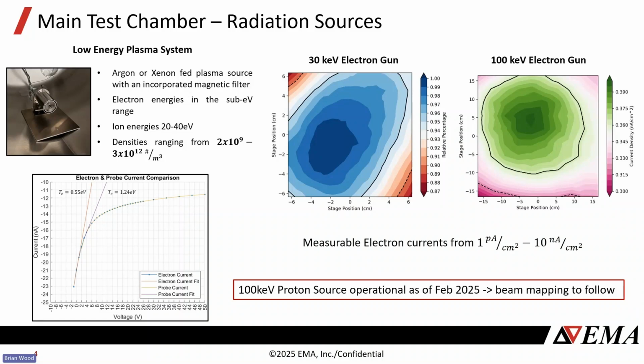Just a little bit more detail on the radiation sources. The low energy plasma system, or LEPS, is basically that LEO simulator. You get ion energies between 20 to 40 eV. It's got a magnetic filter incorporated into it, and what that does is it only allows these sub-eV or 1 eV electrons through the plasma generator, and that's to help better simulate the LEO environment. The densities can range anywhere from, and these are rough numbers, 2 times 10 to the 9 to 3 times 10 to the 12 particles per cubic meter. And that depends on which gas we choose to feed it with.